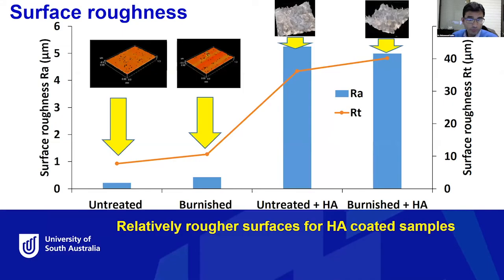So this is our surface topography, and then we have done some surface roughness investigation. We can see that because the HA coating is a bit rough, and because of its plate-like structure, it's not a very uniform, completely dense, homogeneous coating. Because of that, the surface roughness is higher as compared to the untreated or the burnished surface. So it's a bit rough surface. Of course, a rough coating surface can sometimes be beneficial in terms of osteointegration, and also bone growth around the implant. So the surface roughness is a bit higher as compared to the untreated and the burnished surface.